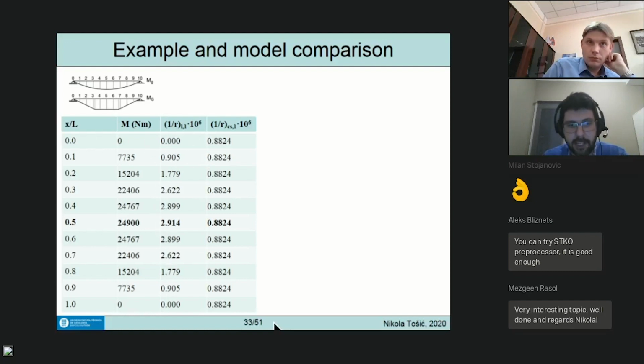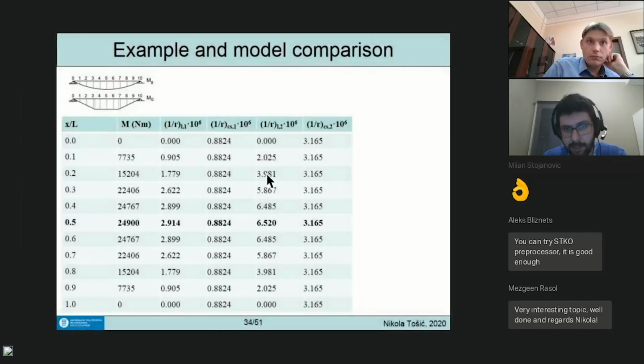And I do that for state 2 as well, so I see how much the curvature is larger for both. And again, for shrinkage, it's constant because of the constant distribution of reinforcement. And importantly, it's positive, in the same direction as from bending.